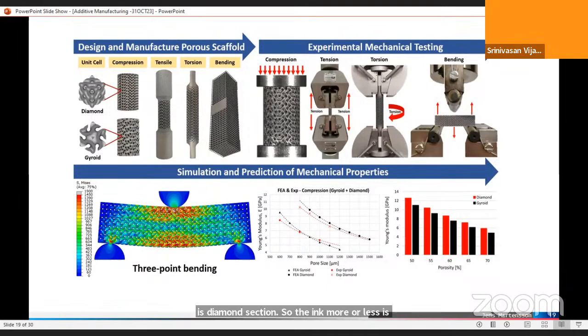See, in the case of aeronautical studies, you need to reduce the porosity and increase the Young's modulus. Whereas for bioimplants, for biomedical applications, you have to reduce the Young's modulus. This is the difference. This plays a key role while selecting the material, while deriving the objectives or problem definition. So two different case studies. In one case study, you reduce the porosity, whereas in the other study, you increase the porosity and reduce the Young's modulus. This is the second case. Both case studies have been done by us.